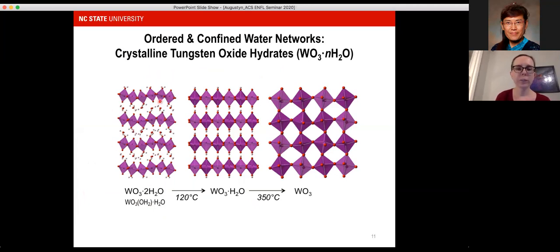The most hydrated form is a layered structure. You have corner sharing octahedra. Tungsten is sitting in the middle of these purple octahedra, surrounded by oxygens as well as water. It's a layered structure, the most hydrated one, with about 7 angstroms interlayer spacing. There's both this lattice water that's hydrogen bonded within the layers, and very uniquely, you also have a water of coordination in this oxide, and that is a slightly longer bond in this octahedra, which explains why you have this significant asymmetry in the structure in these tungsten oxygen bonds.